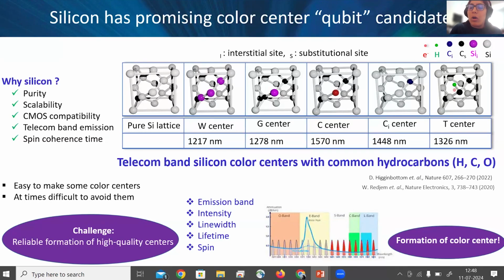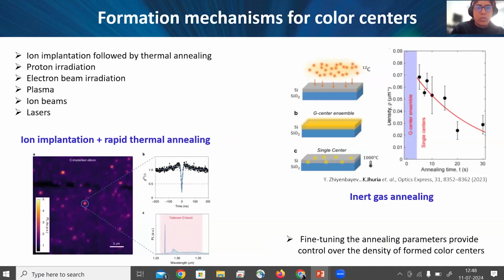Now, when it comes to how we form these color centers, there are actually a bunch of different ways. For example, the most commonly used way is ion implantation to introduce foreign elements in your lattice, and then a thermal annealing process. You can also do direct proton irradiation or electron beam irradiation, and realize color centers in silicon. And it's not just limited to silicon. It goes well with color centers in other materials as well. And then you can also use ion beams, plasmas, or lasers.